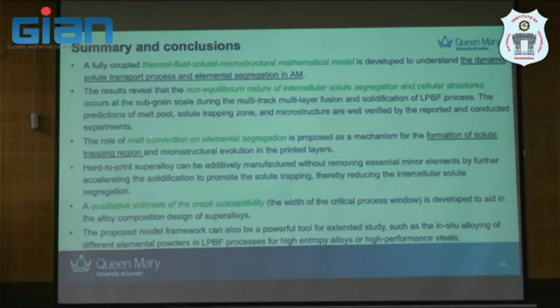The role of melt convection on the elemental segregation is proposed as a mechanism to form the solute trapping region and microstructural evolution. Hard to print superalloy can be additively manufactured without removing essential minor elements by further accelerating the solidification to promote solute trapping and hence reduce intercellular solute segregation. A qualitative estimate of the crack susceptibility in terms of the processing window is developed. I think I showed you before. And I hope this will aid the alloy design of superalloy for the future. So we hope this modeling framework can be powerful too.